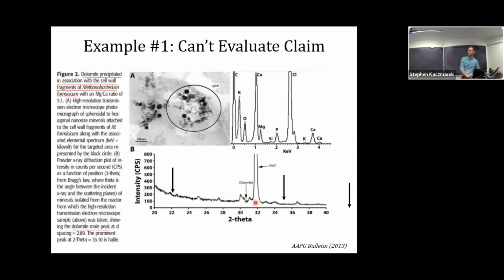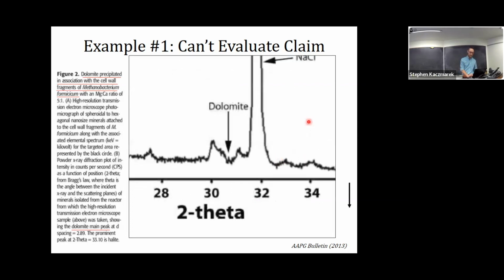So this is where the main dolomite peak is, and this is where the ordering peaks would be. We can't really evaluate the 021 peak. This is where that 015 peak should be, and here's where the other one would be. The fact that this peak is so small suggests that we would never be able to see those minor ordering peaks anyway. So here we have a case where the amount of material made is so small that we really can't use this tool to evaluate the claim. Here's a blow-up of the X-ray diffraction pattern, and that's their dolomite peak right there.